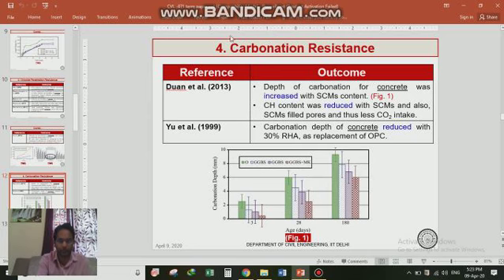Regarding carbonation resistance, Duan et al. in 2013 studied the depth of penetration of carbonation, and it was concluded that the depth increased with SCM contents, as we can see here, and also with age it increased. We can also see that with the addition of SCM, CH content was reduced, which imparts acidity in the concrete, and the pH lowers down, and therefore carbonation resistance is affected. SCM filled pores and thus less CO2 intake.